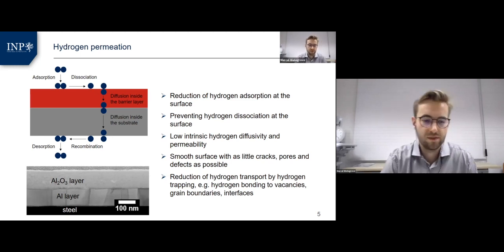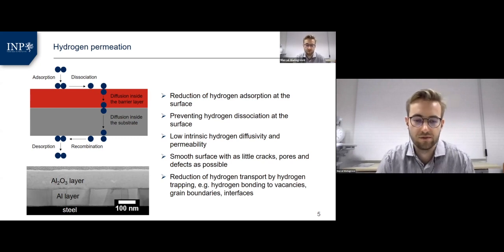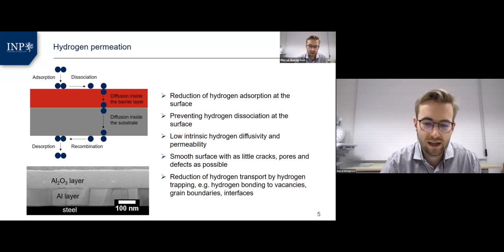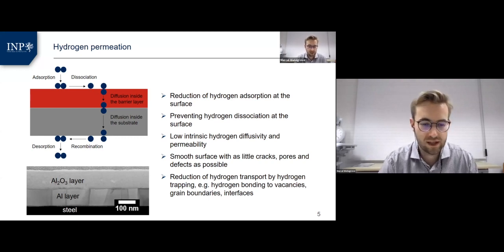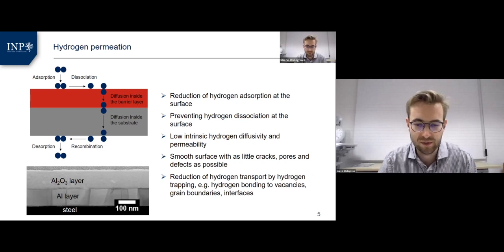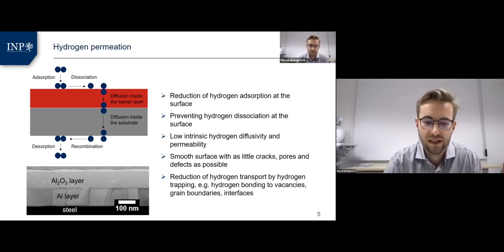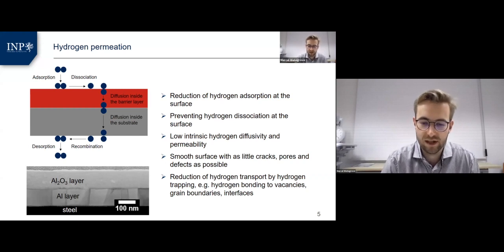And in order to hinder this permeation mechanism, a set of properties are desirable, including reduced hydrogen adsorption at the surface, making surface modifications particularly interesting, a low rate of hydrogen diffusion and low solubility. This is low permeation rates in the bulk, and ideally a smooth surface with as few cracks, pores, and defects as possible. Hydrogen transport can be lowered by a few orders of magnitude by trapping of hydrogen. This is hydrogen bonding to vacancies, interfaces, grain boundaries, and dislocations.